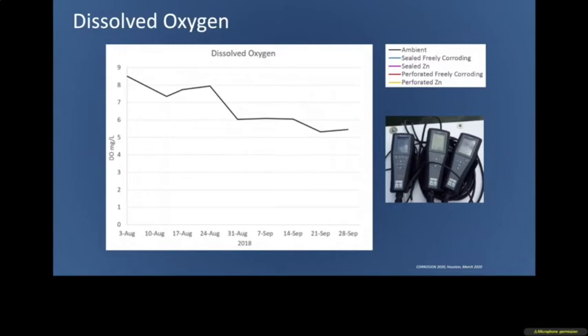Probably the first thing, because it's oxygen that drives corrosion, was the oxygen concentration. And this is the ambient seawater oxygen concentration. You see it declining between August and September, and that is responding to the increase in seawater temperature, at which the saturation levels of oxygen decrease. If we look at the sealed, freely corroding monopile, as you would expect, the oxygen is depleted, but not totally depleted. And this is one of the challenges. To prevent corrosion, you've got to remove all the oxygen present in the water. If we look at the sealed pipe, which had the zinc cathodic protection in, again, we saw a depletion of oxygen, but we actually had leakages within our pipes, like in the monopiles, so some oxygen was present.